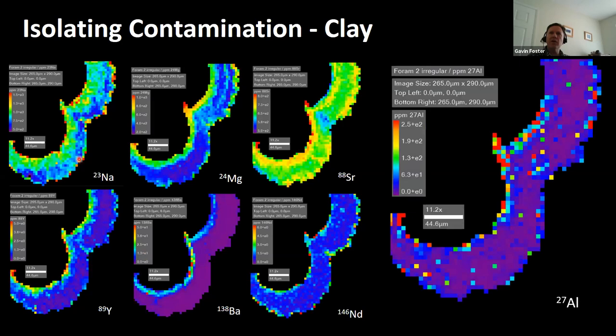And here's aluminium. I should just say that this is varying from thousands of ppm, so about 1,500 ppm sodium, to around 1 ppm or sub ppm neodymium, and the same with the barium. So with aluminium, we see that the majority of the calcite of the foraminifera has got low aluminium. There's the outside of the shell, the inside of the shell, and these areas that have got quite high aluminium. This is probably bits of clay that's made its way into the inside of the test of the foram and is sticking to it. And you see that's associated with elevated sodium, magnesium and neodymium. So if we're going to do any analyses, we'd want to make sure we screen out these high aluminium parts.